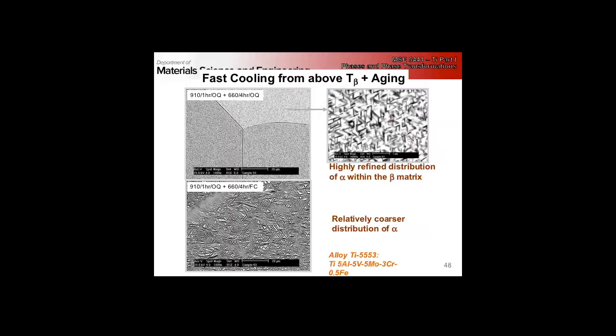From 910, if we fast cool and then age, right? So this is the heat treatment scheme up here. We're above the transus for an hour, oil quench, age at 660 for 4 hours, and then oil quench again.